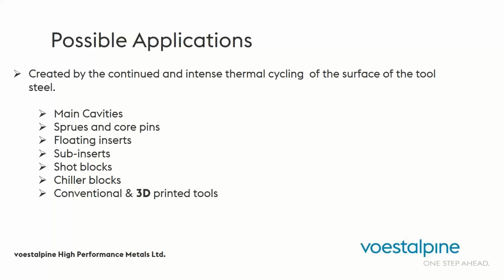Possible applications, main cavities, both sides. Keep in mind, deep ribs are difficult to coat, but if they're away from the gates and so forth, we have many customers that believe in coating on those tools anyways, because it does protect long life. Sprues and core pins, a lot of sprues have IDs running through them from top to bottom, and some of them can be 10, 12 inches long. Again, keep in mind that PVD coating will not penetrate all the way through. If it's a 1-inch hole down the middle, it's only going to go about 1 inch from each end.